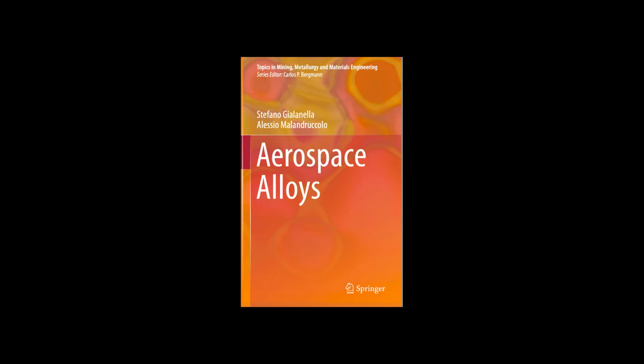And MCrAlX? MCrAlX coatings are overlay coatings, meaning they're deposited on top with a distinct composition, not formed by diffusion with the base metal as much. M is typically nickel, Ni, cobalt, Co, or a combination, NiCo. Cr is chromium for corrosion resistance. Al is aluminum for that alumina scale formation. And X represents a small amount of a reactive element like yttrium, Y, or hafnium, Hf.